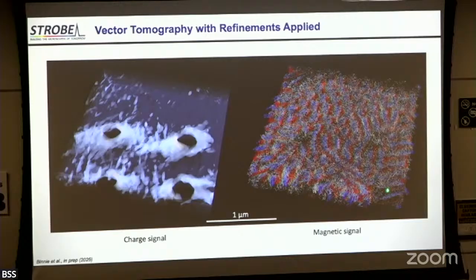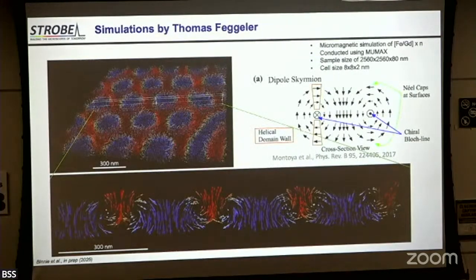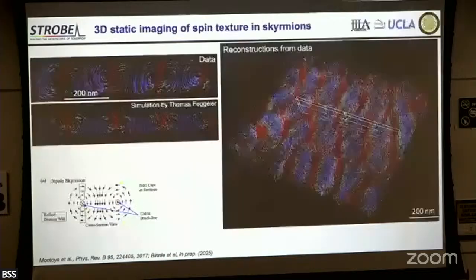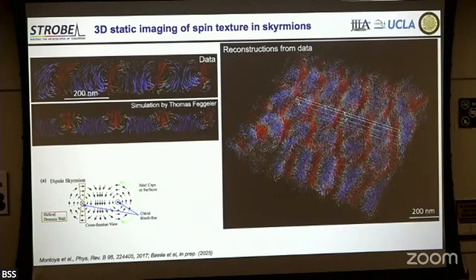You can see the holes here. You can see a little bit of structure in there, but this is a lot dimmer than in the main part of the sample. And then of course, as I said, we have to compare with simulations, and these were done by Thomas Feggeler. He was a postdoc at ALS before moving to Brookhaven. And so these are what we expect to see in terms of the spin texture. And then here is a comparison of our data with the simulations showing reasonable agreement.